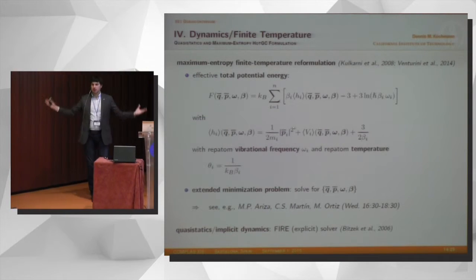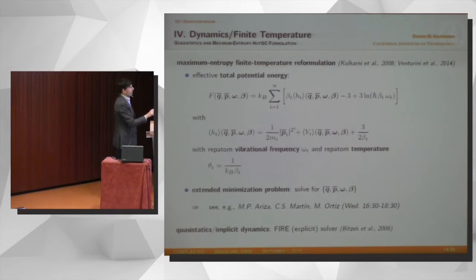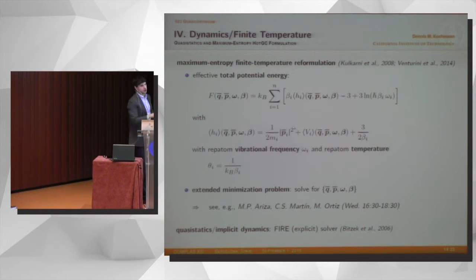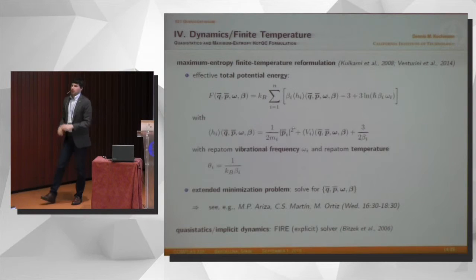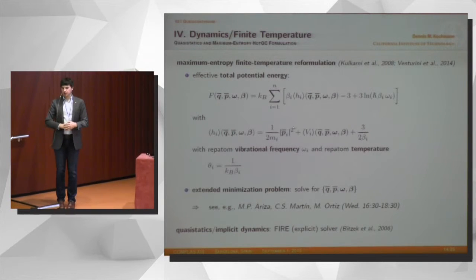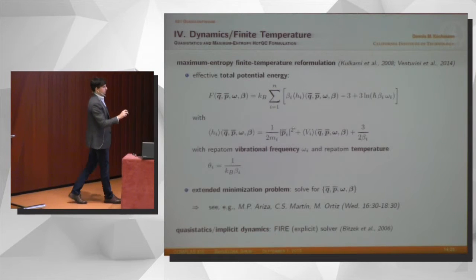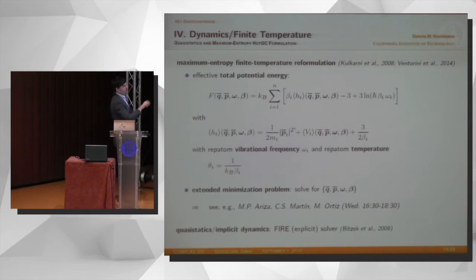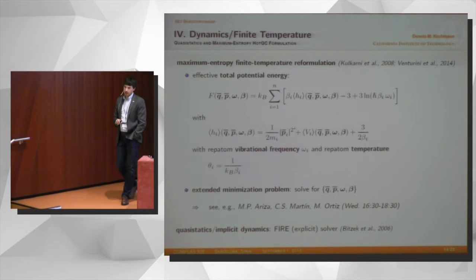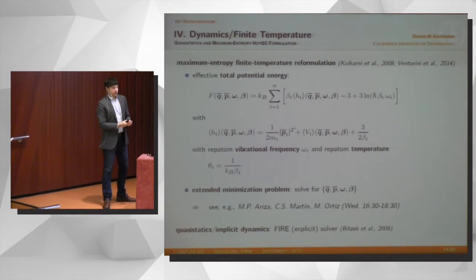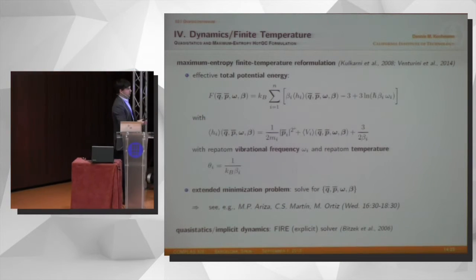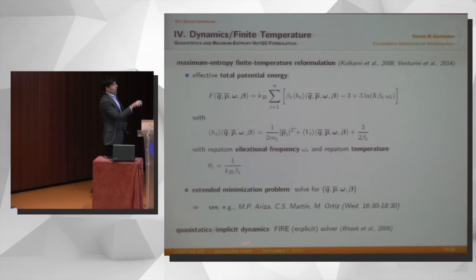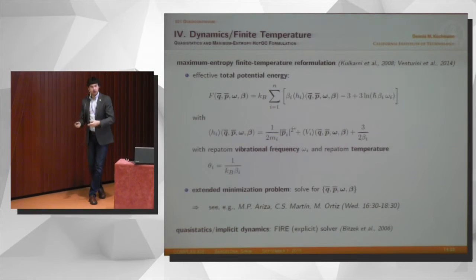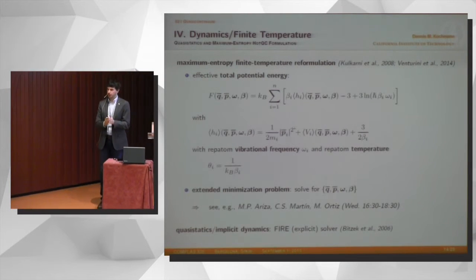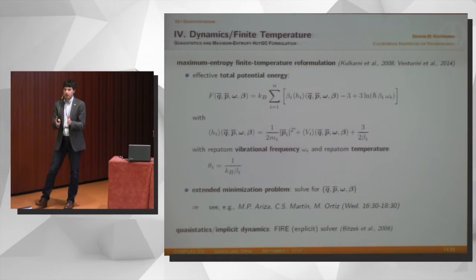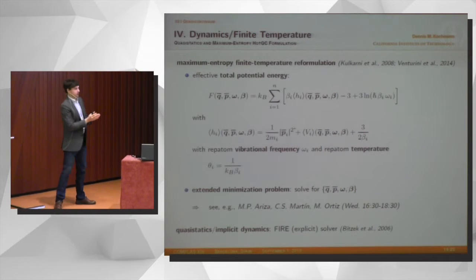And finally, once we've set this all up, we have to solve any problem we're interested in. If you want to do quasi-statics or low temperature, we simply equilibrate the system. We don't use Newton-Raphson or anything like this because the system is simply too big. We have to use an explicit solver. So what we use is called FIRE, which is the Fast Inertial Relaxation Engine by Erik Bitzek and others, which is an explicit relaxation scheme, works pretty much like conjugate gradient but much faster. And if we do dynamics, we can actually solve implicit dynamics here. We use, again, the solver, but by doing implicit dynamics, we can go to bigger time scales. So we're not necessarily tied to the very small time steps that you normally have in atomistics.